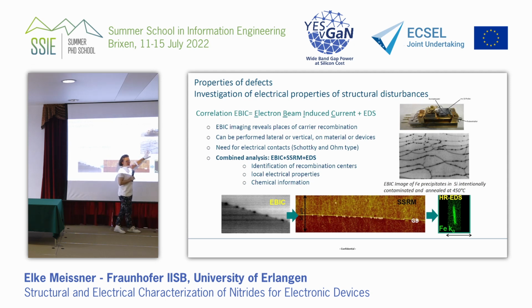So this is the efficiency of the device, what you see finally. So this one is very good, and in such places you have no efficiency. And you can get this magnified and correlated place by place, and you see that these big dots, for example, then you go to the, this is scanning spreading resistance measurement. You also see that the current flow is higher here. Scanning spreading resistance is done at the atomic force microscope. So you put the tip of the AFM on top and you measure the current flow through the material.